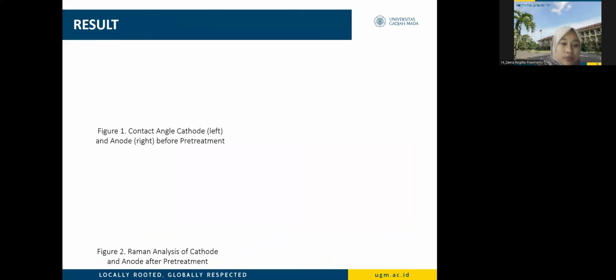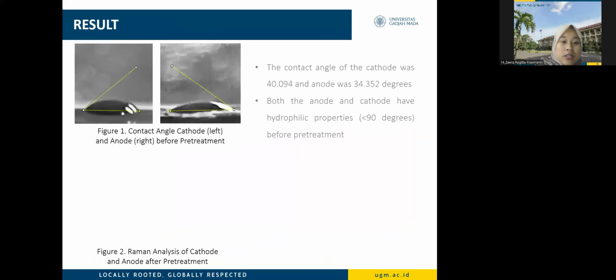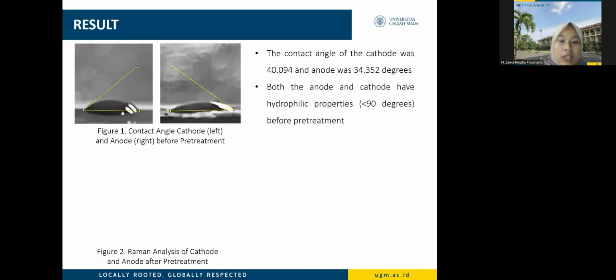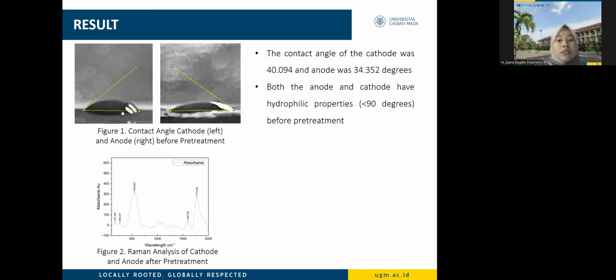The results from this study: first, the contact angle test applied to the anode and cathode before pretreatment. The contact angle of the cathode was 40 and the anode was 34 degrees. That means that both the anode and cathode have hydrophilic properties before pretreatment, which will reduce the effectiveness of flotation.